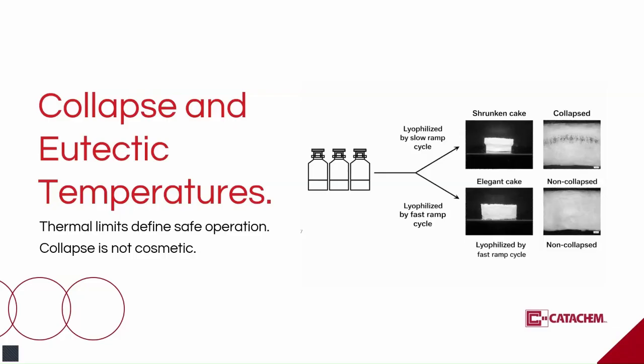That can translate to reduced pore structure, slower reconstitution, higher residual moisture variability, potential loss of activity or potency over time. A product that looks dry can still be compromised if it crossed collapse limits even briefly. So the process question becomes, how do we define and respect those limits? We build the primary drying steps and pressure targets around these limits, and as scale increases, we recharacterize, because on scaling, the thermal pathway changes.